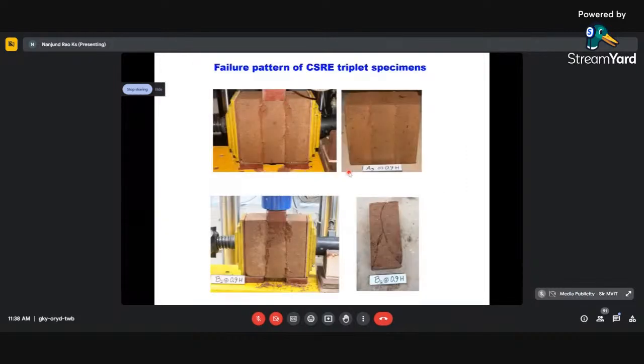In the wet condition, there is no big difference at all. Any enhancement, nothing will happen. And almost all of them have the same C and same phi. So these are the failure patterns of the triplet shear specimens. You can see the end ones, and this is the compacted layer, and here material failure is happening.